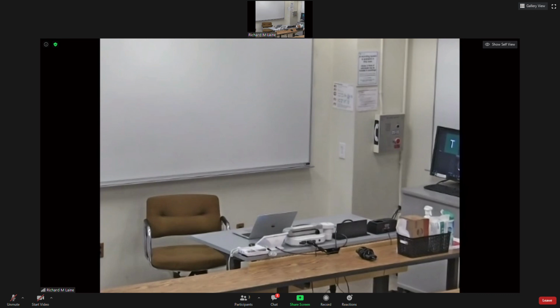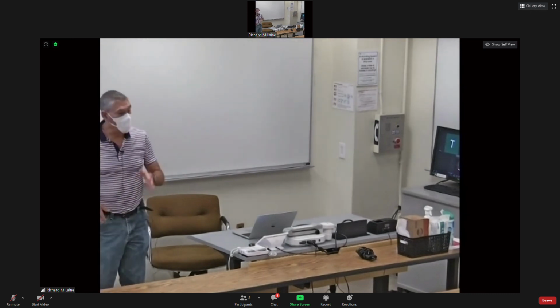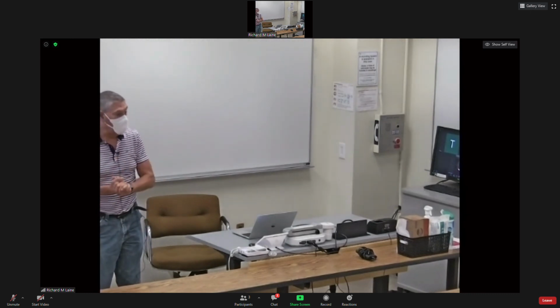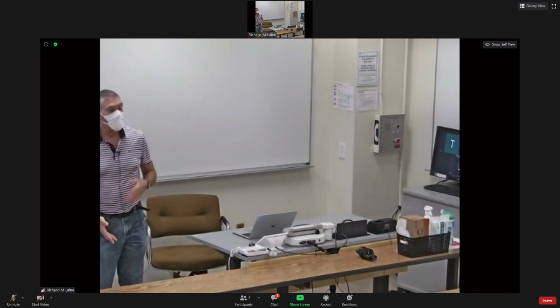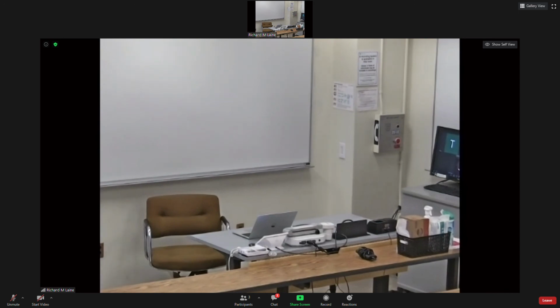But it's found that if you replace germanium with tin, the S3-S3 distance changes. And when it changes, the gap gets smaller, and the ability of lithium to move through is impeded by the smaller gap. So the activation energy for conductivity is increased. So there's a trade-off in adding tin to LGPS. This material is exciting because it can be pressed into a thin film just by mechanical force. It doesn't need to be sintered. So this is why it's of considerable interest to lots of people, because it's a solid electrolyte that doesn't need high temperature processing.